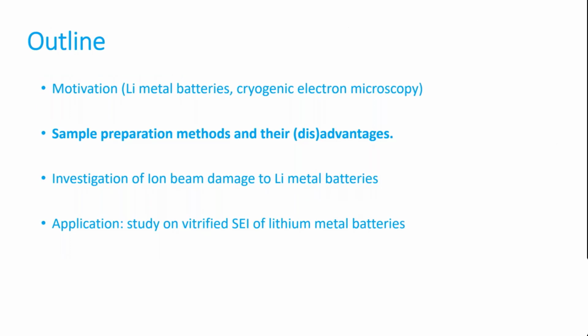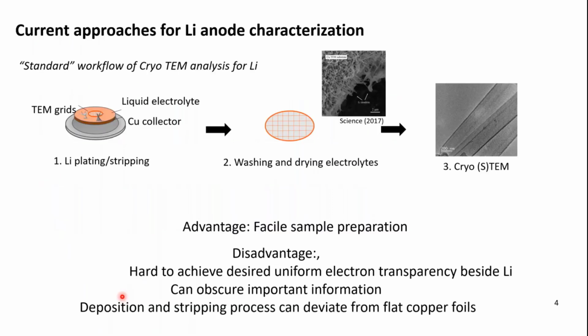Okay, let me talk about sample preparation, how we prepare our samples for cryogenic electron microscopy, and their advantages and disadvantages. So most of the lithium metal characterization has been done in the following way. We can deposit lithium on TEM grids inside a coin cell at a specific capacity. And we can open the coin cells to extract the lithium deposited on copper grids to characterize them. Although this is a very facile sample preparation method, there are several limitations.